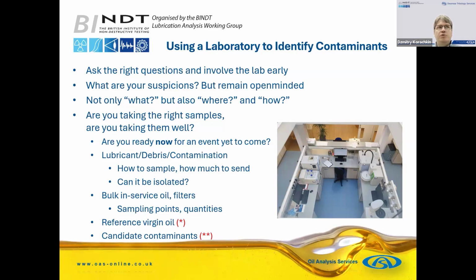So when you send a sample to the lab talking about contamination, you may give your suspicions, or we think it's that, but remain open-minded and allow the lab to suggest test suites which may do an overall condition. We had a sample come in where a client wanted to check if there was AdBlue in fuel. We got that fuel sample. Normally fuel is a fairly clear liquid, maybe slightly yellow or slightly red if it's red diesel and so on. It was black. We tested it. They allowed us to perform the standard test package rather than just looking for AdBlue.